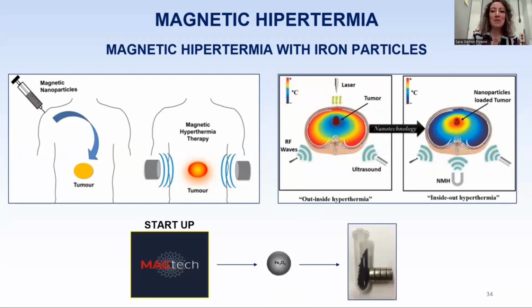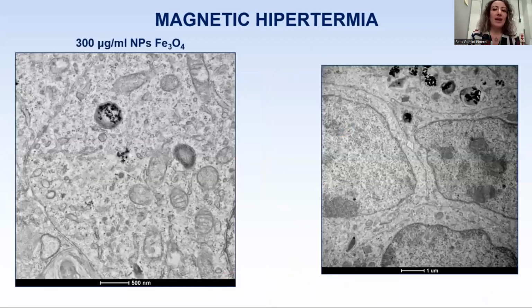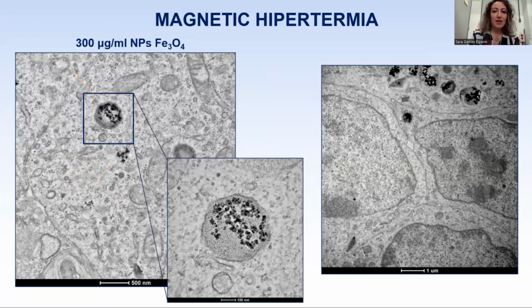And to do this, we are in collaboration with Magtech, a Brazilian startup, to manufacture iron nanoparticles that give us the particles to test hyperthermia for tumor treatment. And we tested the iron nanoparticle in a 3D spheroid tumor model, showing a massive iron internalization with or without membrane around. Moreover, it seems that the outer layer of the cells is able to pass iron nanoparticles to the underlying cells.